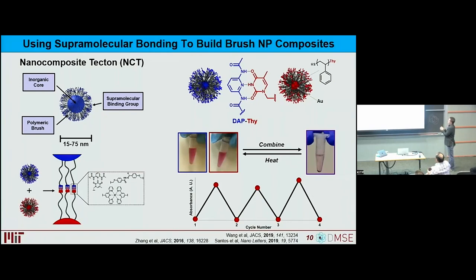It's a gold nanoparticle core. We're going to coat them with polystyrene that has a thiol at one end, so it attaches onto the gold. And at the other end, it either has a thymine or a diaminopyridine group. These form this nice donor-acceptor-donor hydrogen bonding pair, meaning that our assembly can be driven in solution via hydrogen bonding.